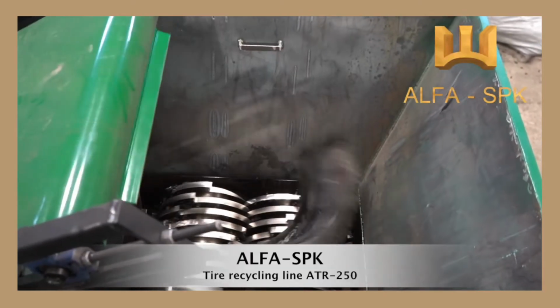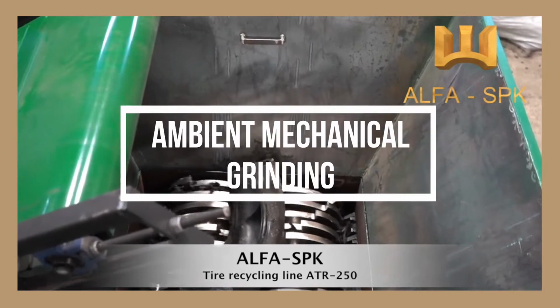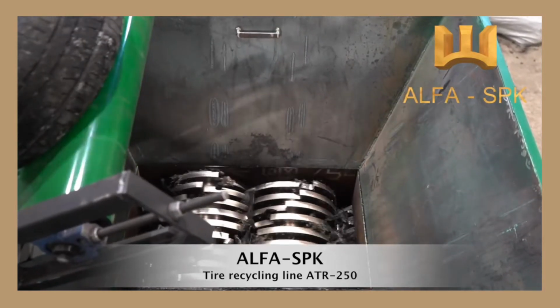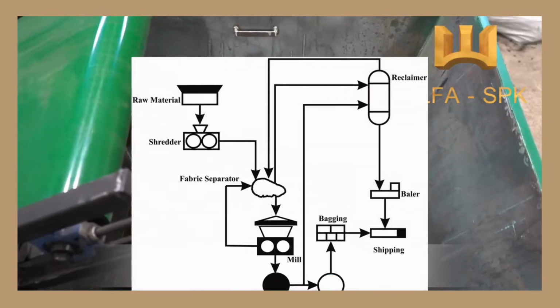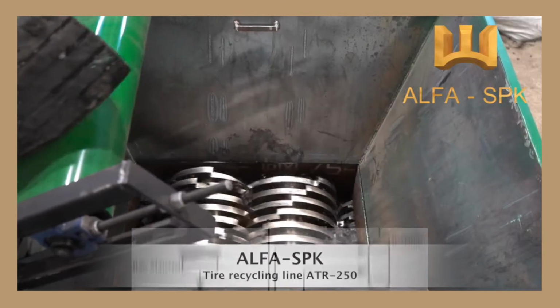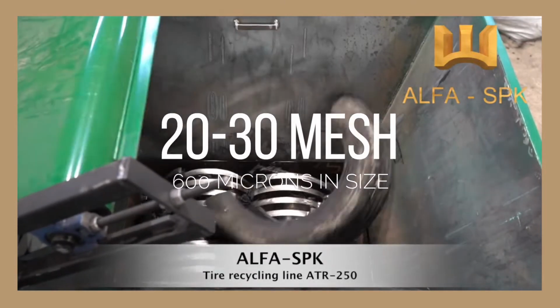The process of pulverizing rubber tires is called ambient mechanical grinding, which is the shredding of rubber tires at above or normal room temperature. Steel wires will be separated using magnets and fibers will be removed by constant shaking and wind sifting. According to EcoGreen, the resulting crumb rubber will have a size of 20 to 30 mesh or 600 microns.